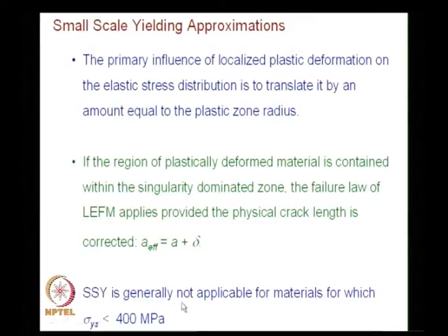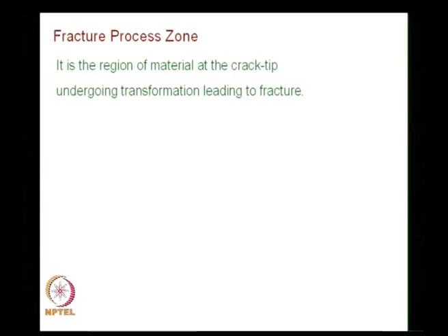SSY is generally not applicable for materials for which the yield strength is less than 400 MPa. So, you have to apply some of these conditions only for high strength alloys, alloys which have yield strength greater than 400 MPa. And what is a fracture process zone? We have also seen that in the picture.